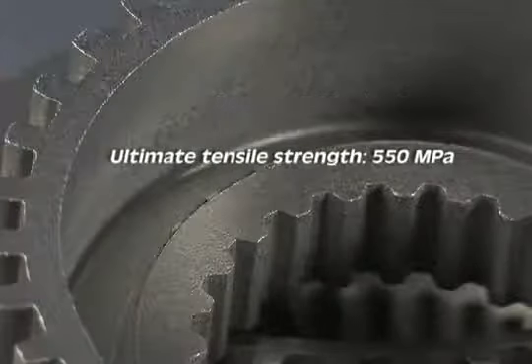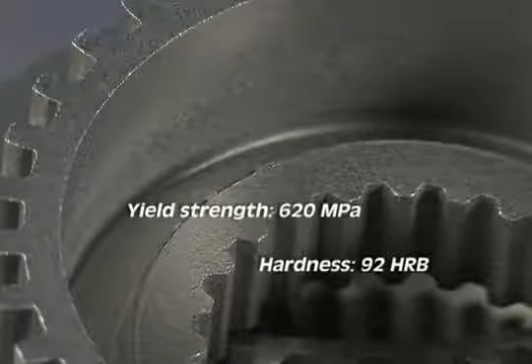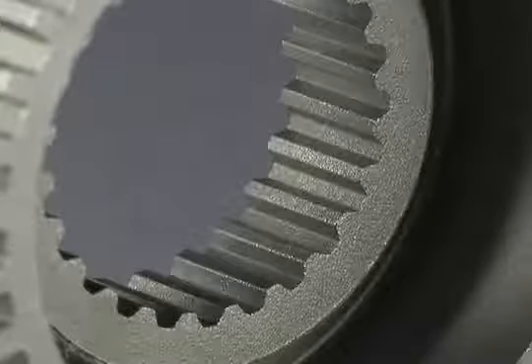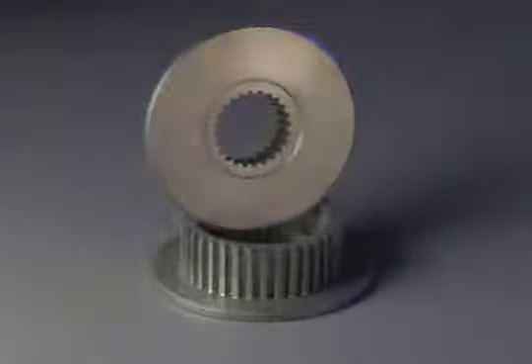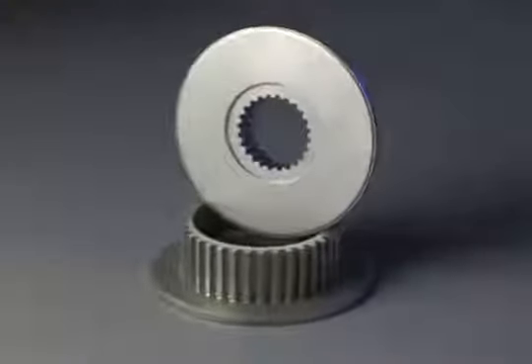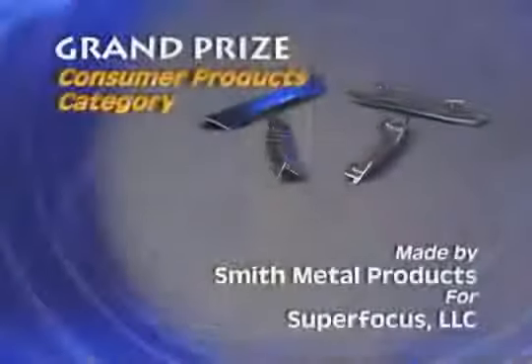Made of a hybrid steel alloy, the part is compacted using 4 lower punches and a stepped single upper punch, coupled with an enhanced powder feed system to facilitate equalized local densities. The part is provided net shape in the as-sintered shot-peened condition. It replaces a machined alternative that is far more expensive.